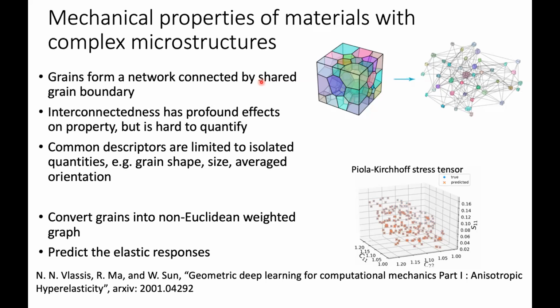range correlation. And by applying the graph neural networks, the authors convert this grain structure into a graph with the grains as nodes and the grain boundaries as the edges. And they use that to predict the elastic response of the materials very accurately.